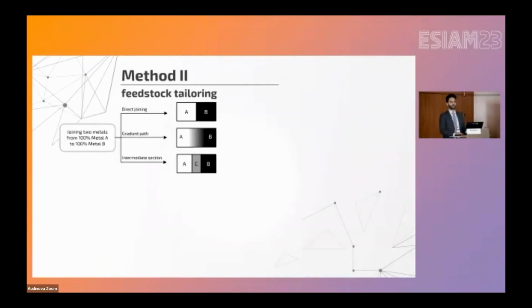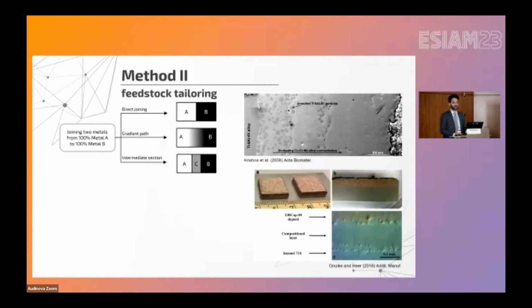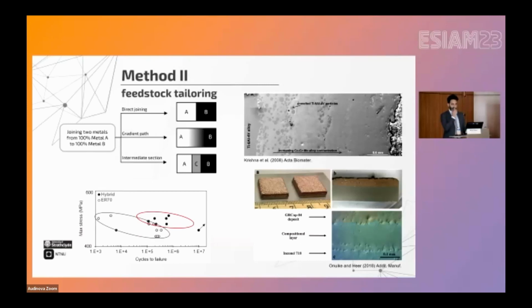we either have this direct joining of the two materials, or we have a gradient path, which is more common for directed energy deposition. There, the mixture is being blended step by step, and we get this gradual change from metal A to metal B. Or we can have an intermediate section with 50-50% volumetric of the two materials in the middle. There are few works on this. People have printed titanium and copper, cobalt chromium, or copper and Inconel, and few other works. What we try to do, of course, this is super preliminary, so it's hard to show anything.